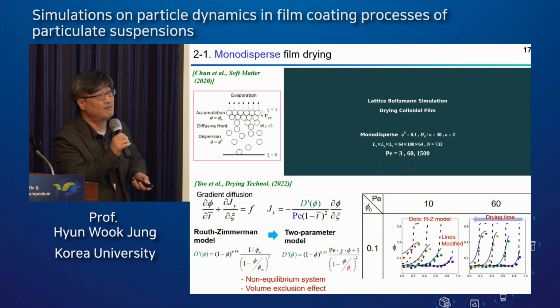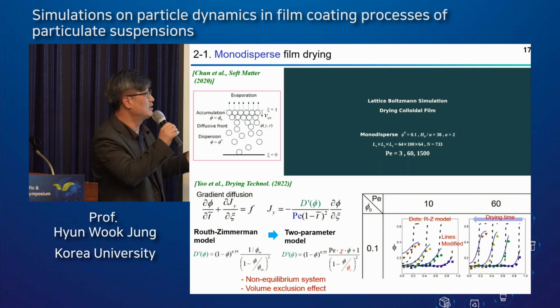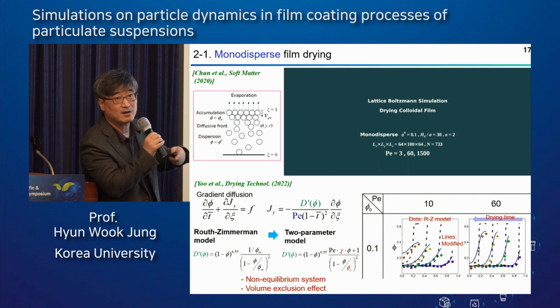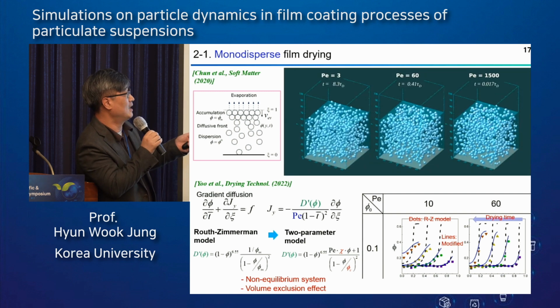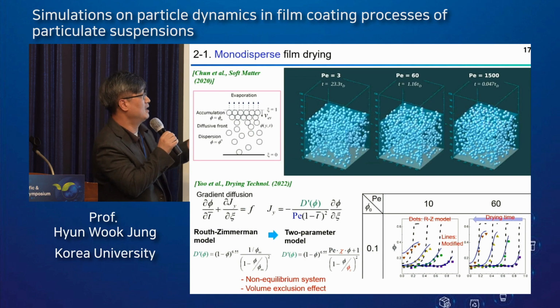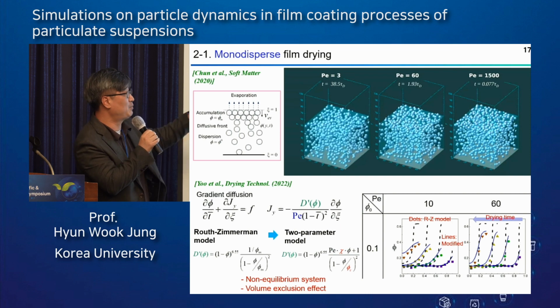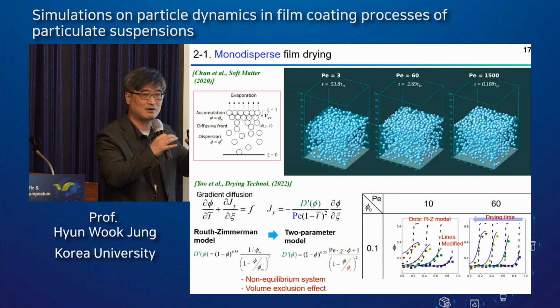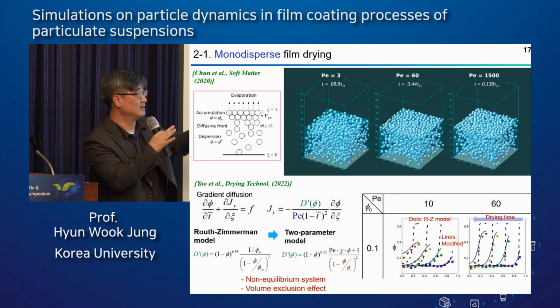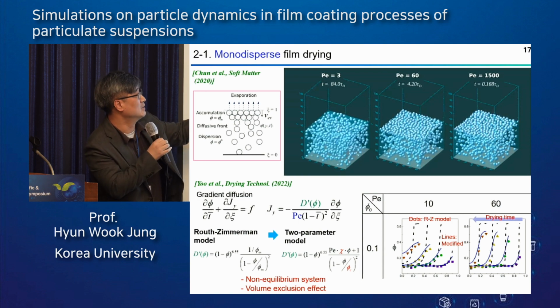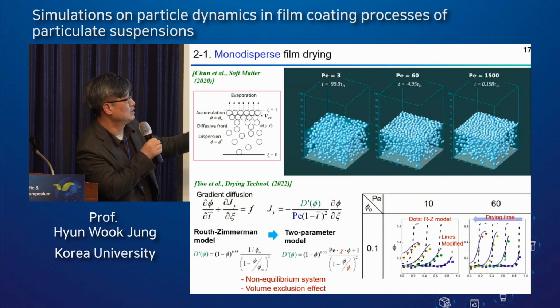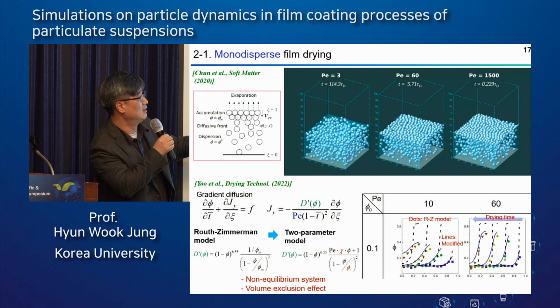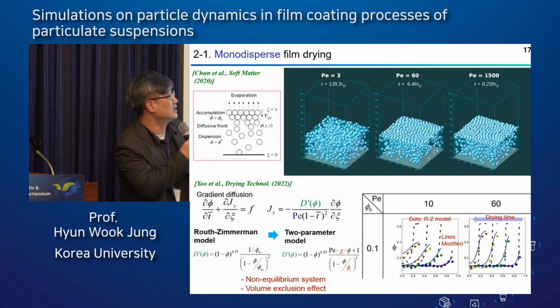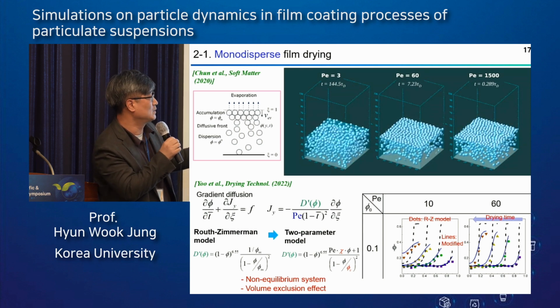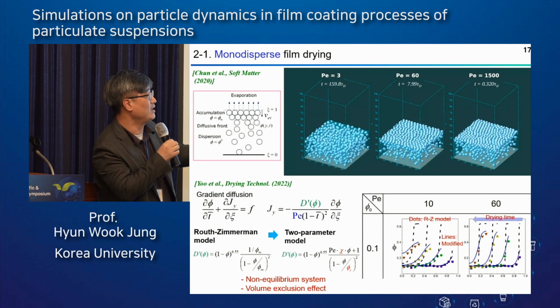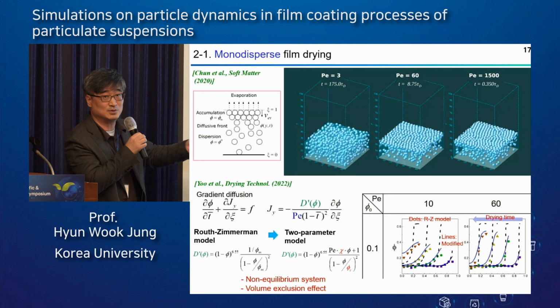The first case is film drying for monodisperse suspension films. We conducted lattice-Boltzmann method simulations by changing the Peclet number for neutrally buoyant particles dispersed in a Newtonian liquid. You can see the transient movement of particles during the drying at different Peclet numbers. The frame time was slightly adjusted so that the interface is in the same position. That is the very slow drying case. At a low Peclet number, you can see particles uniformly distributed along the film height during the drying, whereas at the intermediate or high Peclet number regime, the fast evaporation induced a highly densely packed layer at the top, showing an inhomogeneous particle distribution.